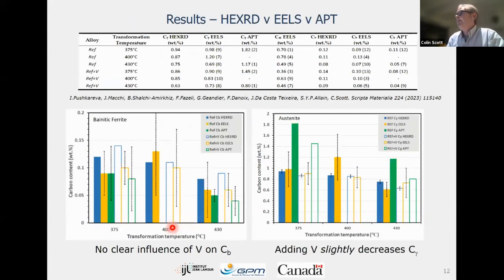So now this is the full data set that we've actually just recently published. So this paper has just come out within the last few weeks in 2023 in Scripta. It compares the high energy X-ray diffraction, the EELS, and the atom probe for the same samples. And what's kind of interesting about this study is it's the first time all these three techniques have been used in parallel. And it's also one of the few studies where you have a significant amount of statistics in the data. So the numbers in the parentheses, these are the number of samples or the number of areas that we've actually examined. So you can see, for example, the atom probe areas, we've got 12 different areas for one sample, for example, there.